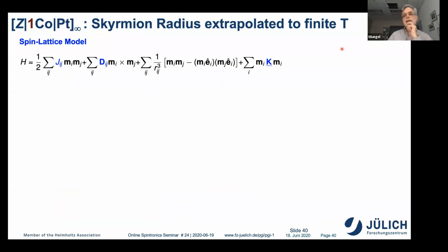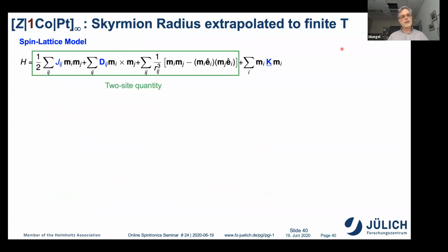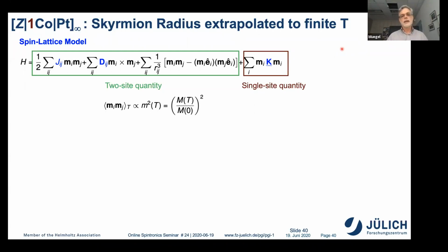Now, let me make one or two more comments. One is the finite temperature. So far, everything was T equals 0 calculation. If you look at our spin lattice model, we have a couple of quantities which are two-site quantities, and we have one quantity which is a single-site quantity. If you now take the thermal correlations into account, you see that these quantities roughly scale proportional to the magnetization as function of temperature to the magnetization at 0 temperature squared, whereas this quantity scales with the third power.